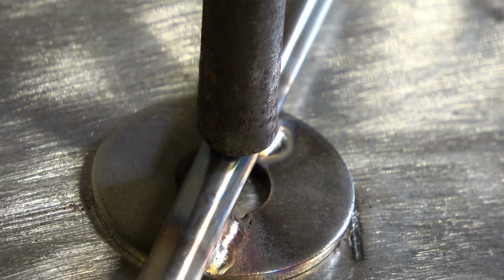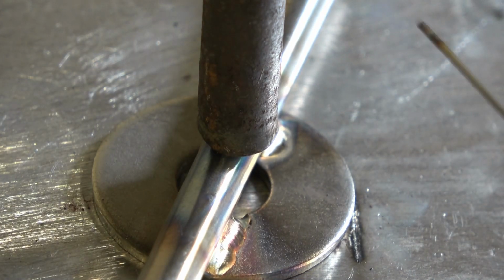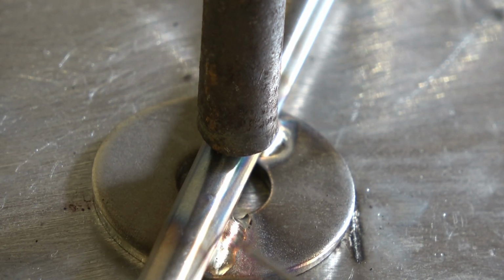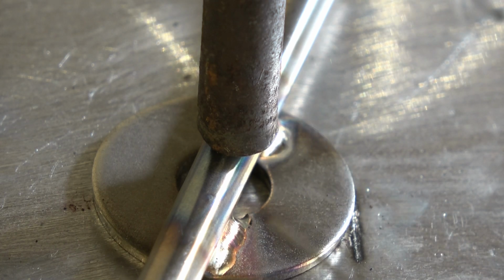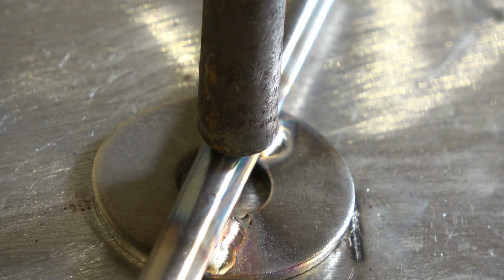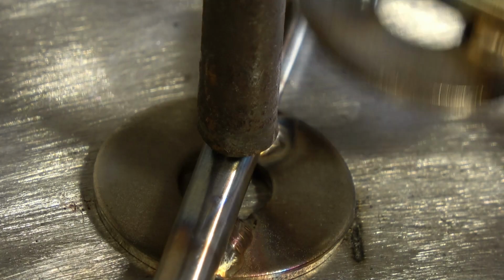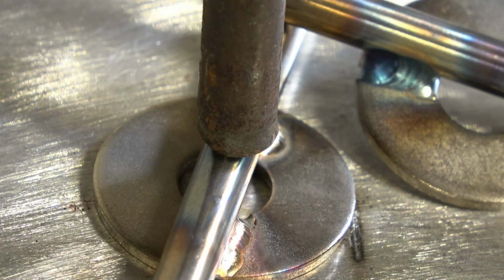On that weld there, the arc was a lot tighter. There's obviously been less heat put in because that's the colour I'm supposed to get, the golden straw colour, not a blue colour. See the difference on the heat input on the two welds.